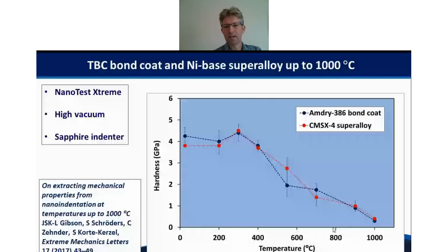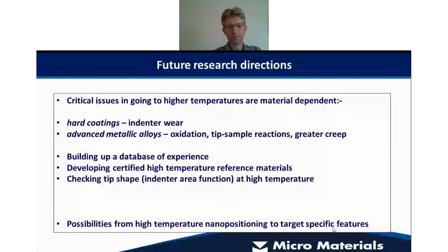Also at Aachen, they've extended this work, and they've used their Nanotest Extreme to do tests in high vacuum with a sapphire indenter on both the bond coat and also the superalloy substrate. We can see there that the mechanical properties are reasonably similar. Actually, the superalloy substrate softens less quickly typically than the bond coat, but nevertheless, it's quite consistent data. And that's the first time in the world that we've been able to use nanoindentation to reach 1,000 degrees and get highly quantitative data throughout that temperature range. So they should be applauded for that.